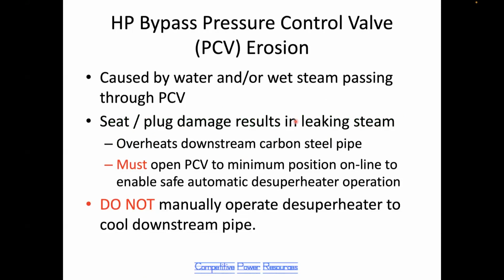Okay, now we will talk a moment about the HP bypass pressure control valve. Over the last, I would say, 8 or 9 years, this has become more and more common. The erosion that we see is caused by water or wet steam passing through the HP pressure control valve. When the water passes through, it erodes the seating surfaces. It also erodes other parts of the valve in severe cases, the cage and the plug.